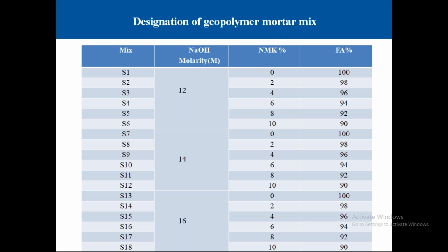The nanometakaolin was varied from 0 to 10% with different molarity 12, 14, and 16. Nanometakaolin was replaced with fly ash. First of all, nanometakaolin was 0 and fly ash was 100%. Then for 2, fly ash was 98; 4, 96; 6, 94; 8, 92; 10, and 90. So S1 to S6 correspond to 12 molarity, S7 to S12 correspond to 14 molarity, and S13 to S18 correspond to 16 molarity. So this was the designation of the geopolymer mortar mix.